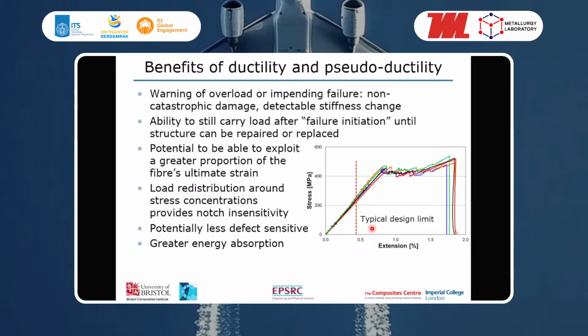So in that case, that's why this failure strain is only about 0.4, which is 4 or 5 times less than the strain that the material can really take. That's a typical design strain. So in this case, the idea is that we could maybe go a bit beyond that by making it less susceptible to damage or to notches. So it depends on the application. For ultimate strength, use the carbon fiber on its own, but if you want a more gradual response and less notch sensitivity, then these hybrids can be an advantage.